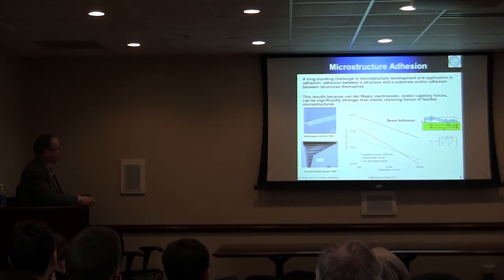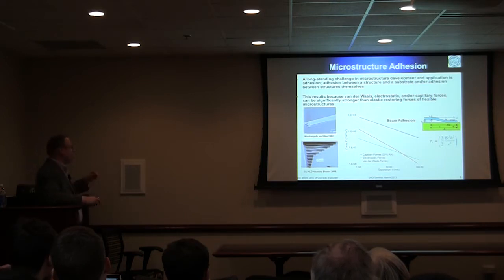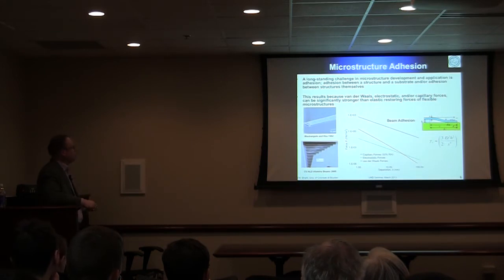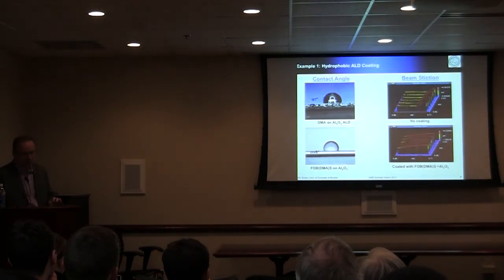And you can measure the adhesion of the beam relative to the substrate, the length of the adhesion. Based on this equation, one can determine the adhesion energy. It doesn't tell you which force is involved, but at least it gives you adhesion energy. So using this, one can actually study how different films would behave.